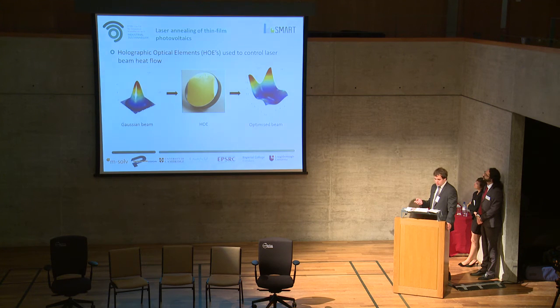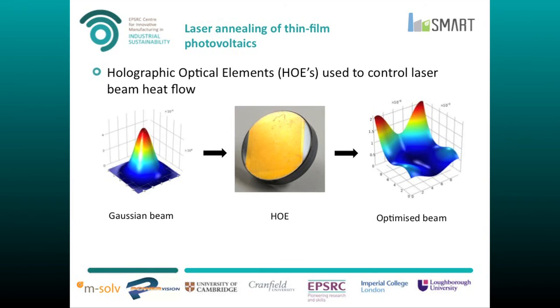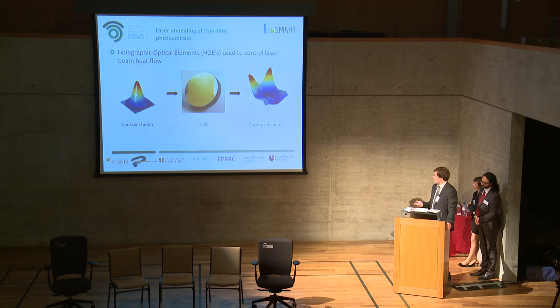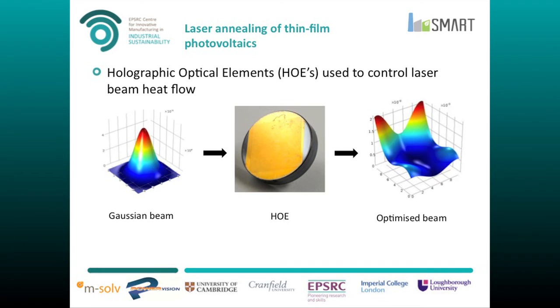Then what we do is we use what are called holographic optical elements. So these are a new type of optic, which has been used for other material processing applications. This is the first time it's been used for cadmium telluride. And what it allows us to do is customize the profile of the laser beam to optimize heat flow. So a standard laser beam is what's called a Gaussian shape. So it's a circular spot, like this laser pen, and the heat is concentrated in the center. So a Gaussian laser beam: circular spot, uneven heat profile.